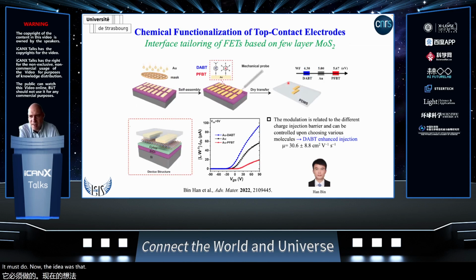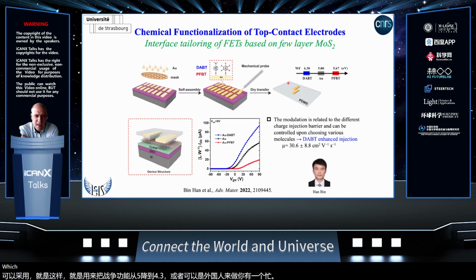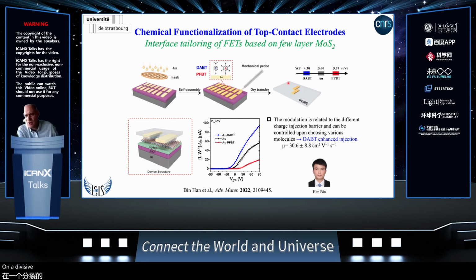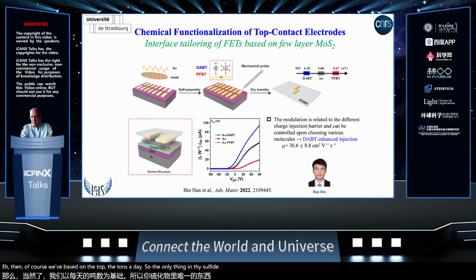Now, the idea was that he first created this kind of small gold flakes, and using a mask, this kind of patterns of gold has been functionalized with different types of thiolated molecule, which can be a dopant that is used in order to lower the work function from 5 to 4.3, or can be a fluorinated derivative, which indeed is used in order to increase the work function up to 5.6. And then he was able to perform a dry transfer process and turn it upside down on a device in which we use Cytop covering the silicon dioxide, and we chose this because of its low surface energy, the near absence of trap states and absence of dangling bonds. Then, of course, we placed on the top the molybdenum disulfide, and transferred the asymmetric electrodes.